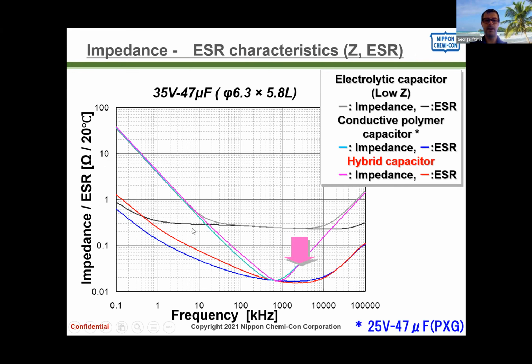This is essentially a very similar capacitor. So if you look at the bottom, the red and the blue, this is ESR basically. And you'll see that the polymers and the hybrids, the bottom curves, are essentially very similar in terms of ESR. And of course, liquid electrolytic capacitors are an order of magnitude higher than the hybrids and the polymers. And this is typical behavior. The only thing that's going to really change is the low point, and a little bit of distribution depending on what size you're looking at.